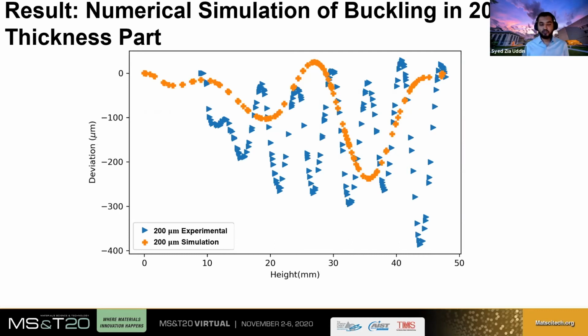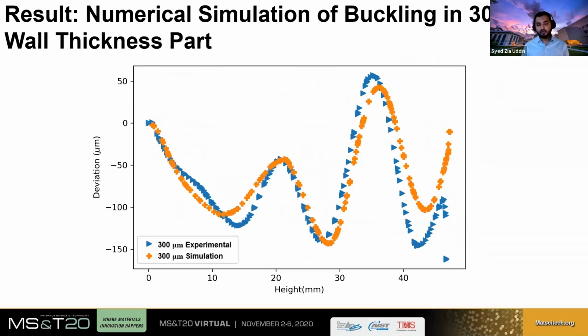And we used Autodesk's Netfabb Local Simulation for additive manufacturing for performing these simulations. So if this looks bad, then there is some good news with the 300 micron wall thickness, where we can see that there is a very good correspondence between the simulation and the experiments. So we're still investigating where the 200 micron wall thickness simulation does not match that well with the experimental results,